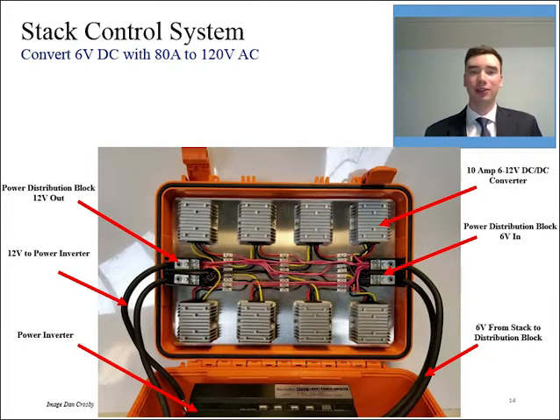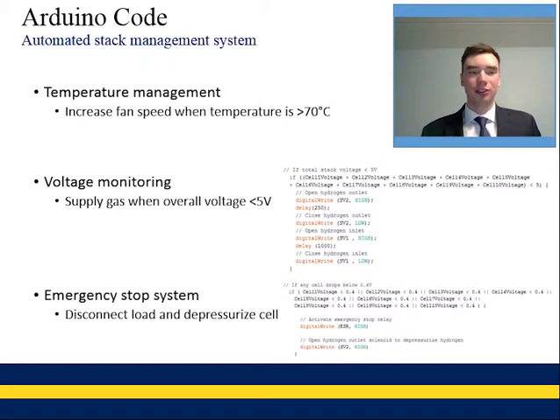So along with this project, we designed a control system for the stack. Shown here is our power conversion box. We're going to convert the 6-volt DC input at around 80 amps to 100 amps depending on our performance, and then we're going to change that to 120 volts AC. We do that through these 6 to 12 volt DC converters, and then we take the 12 volt output from that and power a power inverter and get 120 volts AC out of it, which can power most household appliances. Along with this control system, we have an automated stack management system. We used an Arduino Mega 2560 to control this stack.